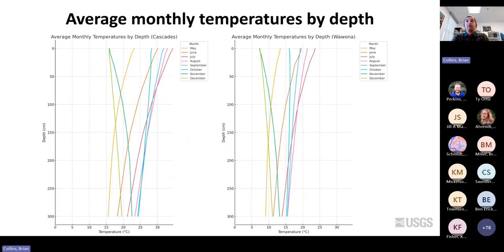If you look at the average monthly temperatures by depth on the two sides, on the left side we have the south-facing slope, Cascade side. On the right graph, we have the north-facing slope at the Wawona side. You can see a similar pattern, but shifted by about 10 degrees, as the south-facing side is about 10 degrees warmer than the north-facing one. What you can notice here is that when the curve of the graph is going to the right side, it means that we are in the warming period, and if it's going to the left side, we are in the cooling period.